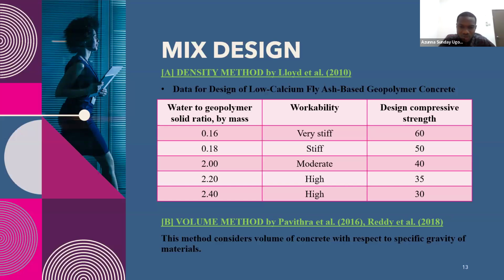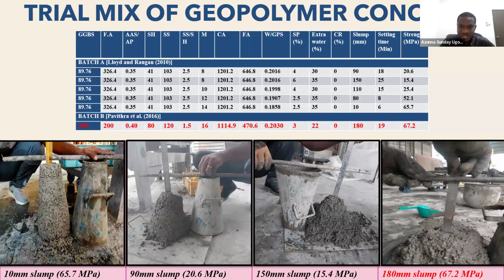Then there's another method, the volume method by Pavithra. This method, on the other hand, is just like normal concrete design, where you use the maximum size of your aggregate to determine the water content for your mix. Here you use the volume of concrete to determine the constituents of the concrete: your fine aggregate, your coarse aggregate, your binders, and your alkaline solution. And you also use the specific gravity to multiply them, which helps you to know the exact quantity that you will be using for your mix. Now, in the next page, I'm going to show you trials I did with both methods.